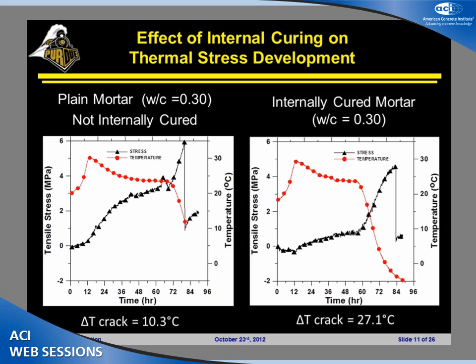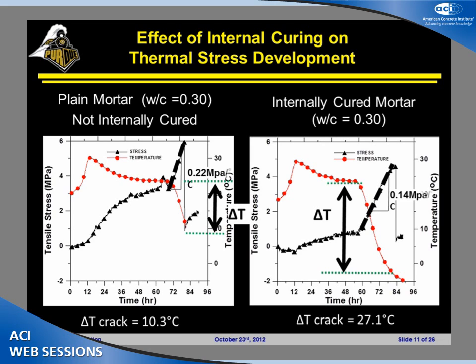And one of the real reasons that this is very important is because we have big temperature differences that are taking place in samples. One, because of the fact that we're losing heat to the atmosphere, but also we have heat of hydration buildup in the samples as well. So building in a little extra capacity really can help us out substantially. The other thing that I'll point out is the stress development rates in both of these systems are not the same.